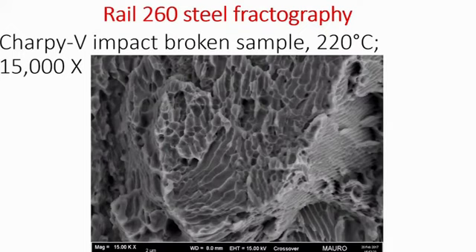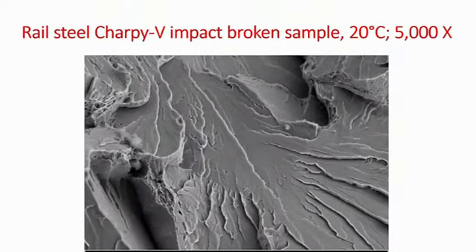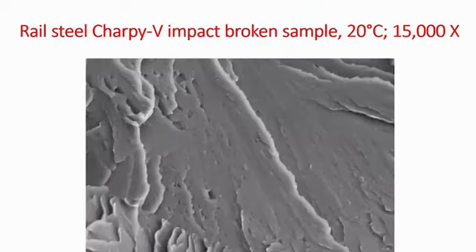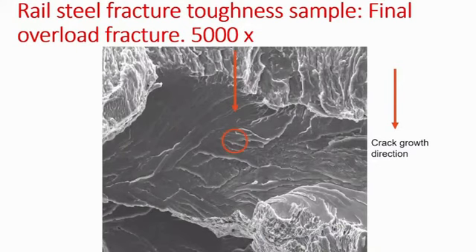With modern SEMs, you can see better what happens at 220 degrees C when you have a Charpy-V impact broken sample of rail steel. But when you go to low temperature, the same steel, you can really see that it is definitely a brittle fracture, a brittle cleavage fracture. And this is at the maximum speed. When you reduce the speed a little bit, you still have almost all cleavage fracture. And so you can be sure that at room temperature, you should see cleavage fracture.